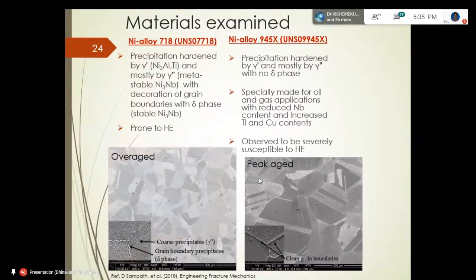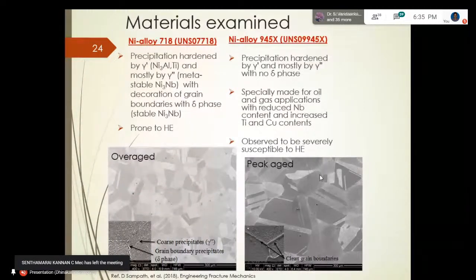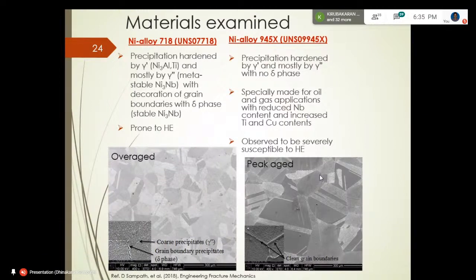So yes, actually, there is a well-established test method for measuring hydrogen diffusivity. There are a couple of methods. One is hydrogen permeation test, where they have two electrochemical cells on either side of thin material of your choice. So in your case, you're going to use additively manufactured specimen. So the hydrogen permeation test can get you hydrogen diffusivity.